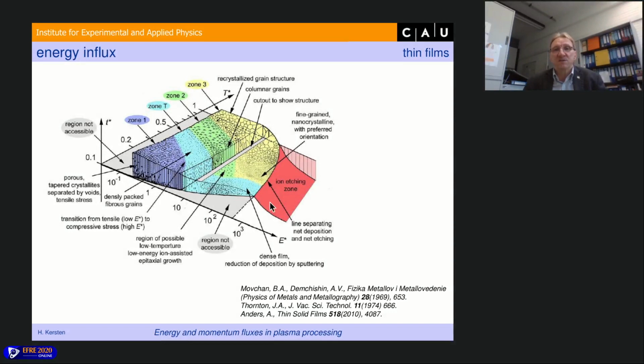This is the so-called Thornton model of deposition of thin films, but this model was originally introduced by Russian colleagues, by Movchan and Demchishin, already in 1969, and later Thornton improved this model, and recently, a few years ago, Andre Anders in Leipzig modified this model again. And what is important, if you deposit thin films, you can see here the temperature of the substrate or the surface in units of the melting temperature. So 1 means it's the melting temperature, and here it's 20% of the melting temperature. And of course, if you heat your substrate during the deposition of the thin film, you can influence the morphology. So you can go from amorphous to microcrystalline to crystalline structures of your thin film.